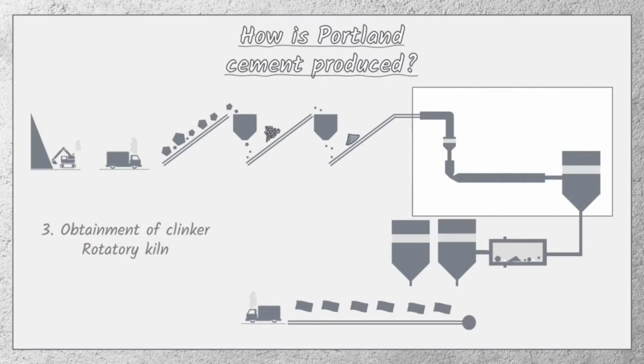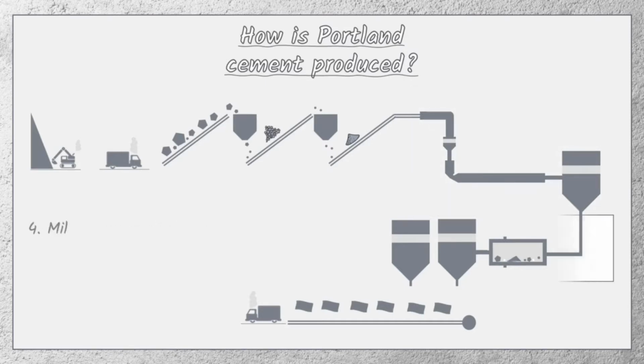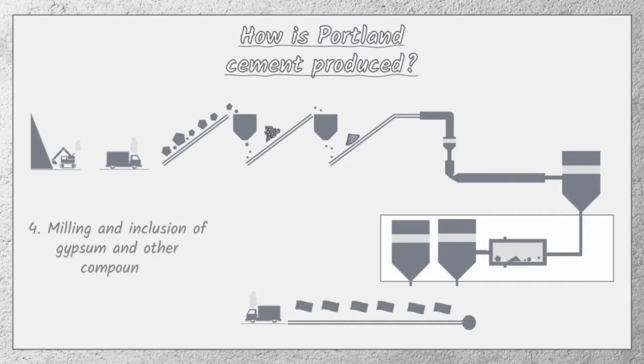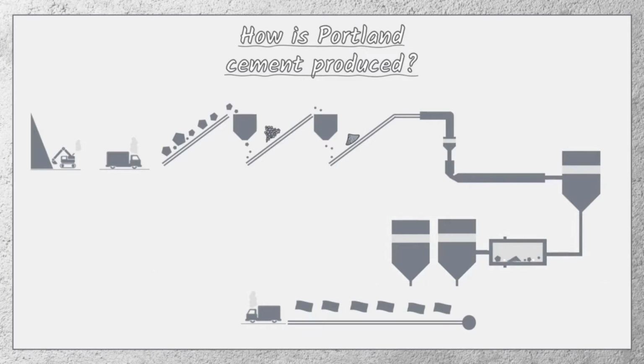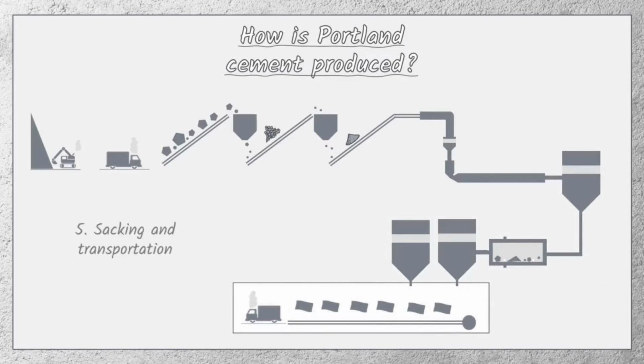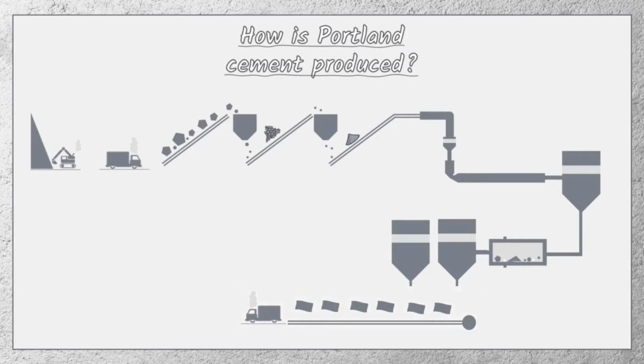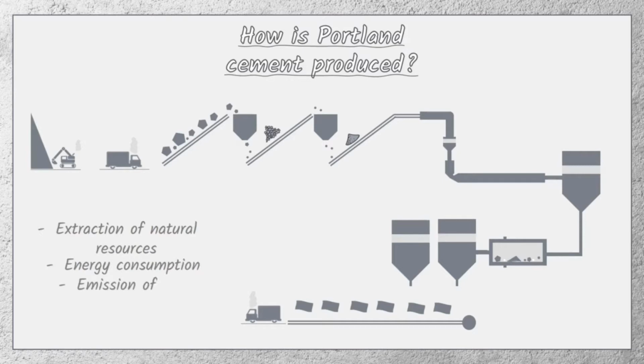These kilns are lighted at temperatures above 1400 degrees, and this stage liberates the largest portion of carbon dioxide of the whole process. After burning, clinker is kept in silos to promote homogeneity of humidity before further stages. Further on, clinker is mixed with other compounds such as gypsum and admixtures and maintained in silos for final homogenization. Cement is then finally sacked and transported to its final destination, which can be construction stores, construction sites, or other places. This is the whole production chain of Portland cement, a raw material which, although plays an essential role in our lives, has a large carbon footprint in all stages of its production, with the extraction of natural resources, consumption of high levels of energy, and emission of carbon dioxide.